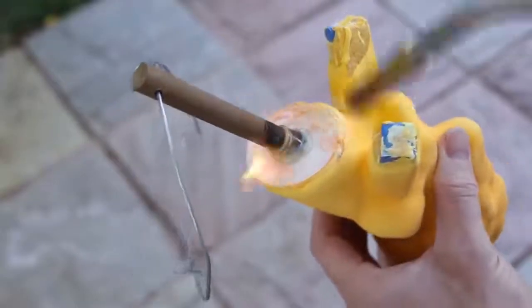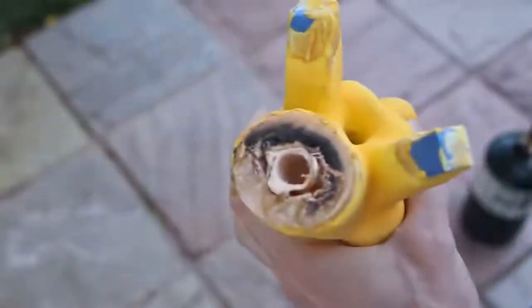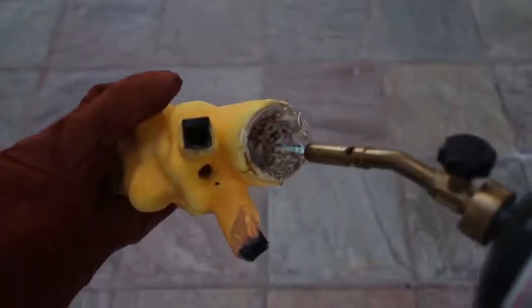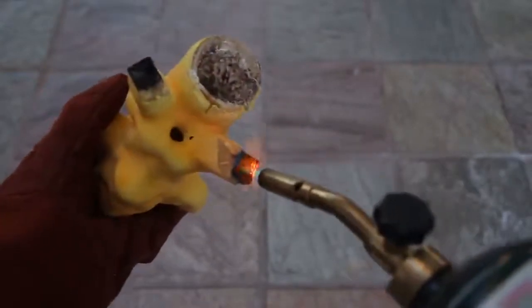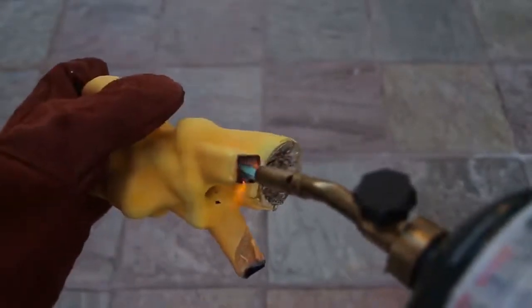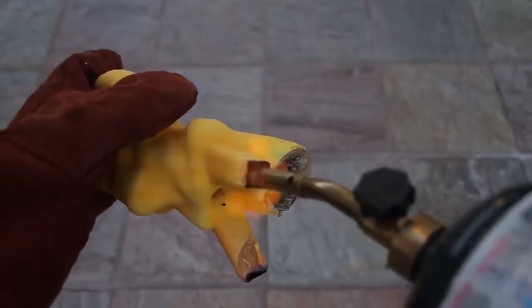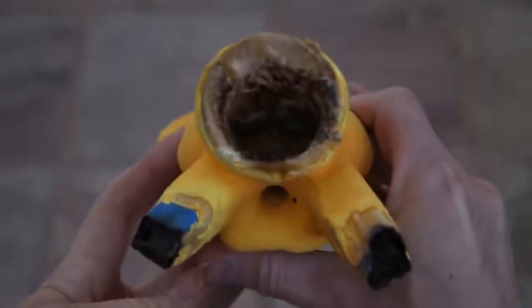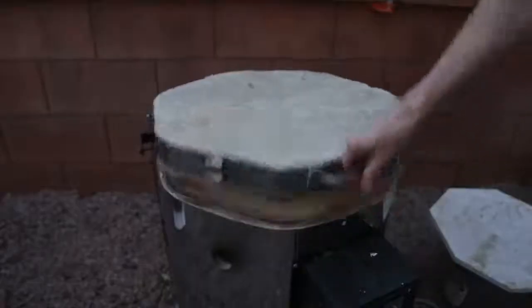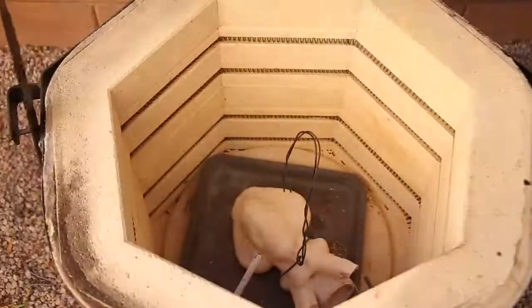Next, I removed the wooden handle and as much plastic as I could. This will help prevent pressure from building up and cracking the shell during the next step. After the shell was completely dry, I placed it into my kiln to burn out the wax and plastic, as well as vitrify the shell, which turns it into a ceramic that can withstand the heat of the molten metal. I baked the shell for a few hours at about 1700 degrees Fahrenheit, or 900 degrees Celsius.